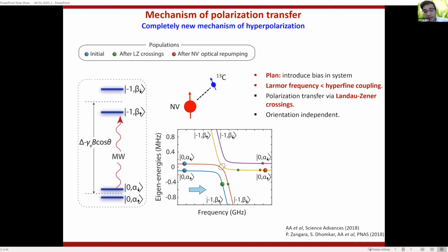So what happens is that in these two spin states, the traversal through one of the spin states is adiabatic, and the traversal through the other spin state is diabatic. And as you traverse the system, most of the population that's in the spin up state remains in spin up because that's adiabatic. But the population in spin down splits between down and up. And over time, you build up a ratchet, and all the population is transported to this down state. And this is what gives rise to hyperpolarization. So, at its heart, it's a very simple mechanism, but it's the same thing that works in all hyperpolarization mechanisms. It's a means by which you can build up a bias in the system.